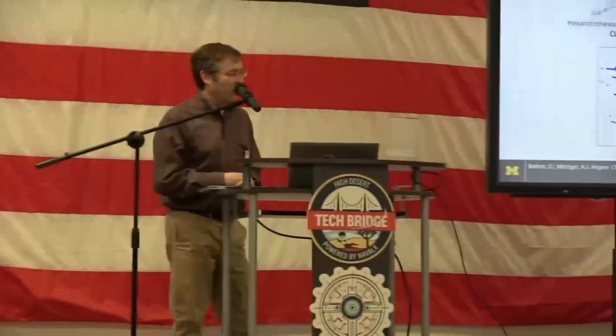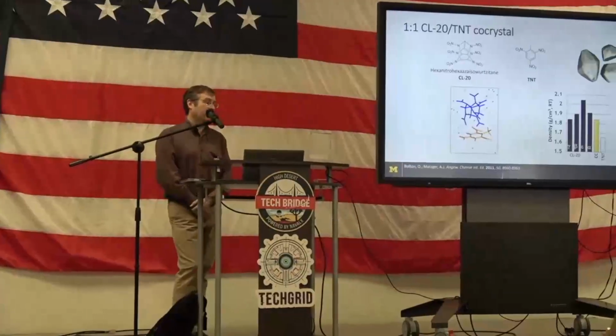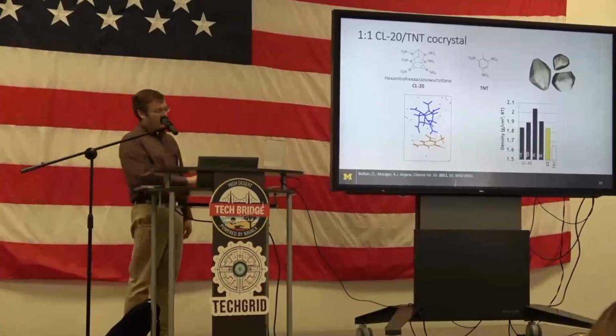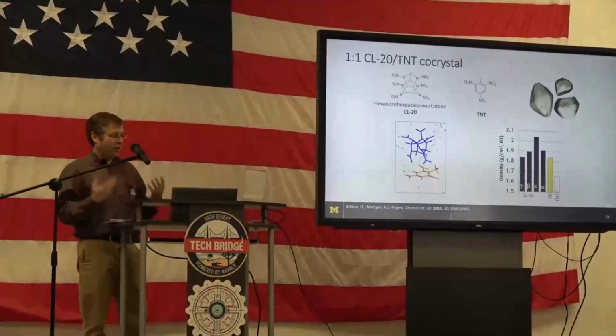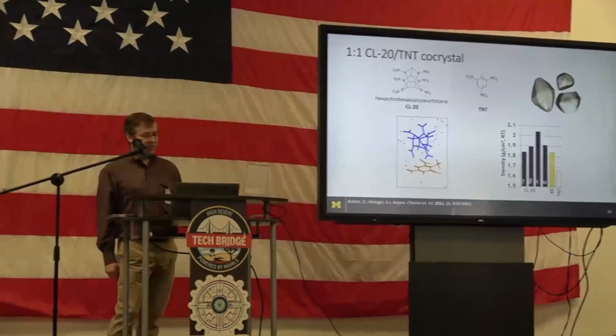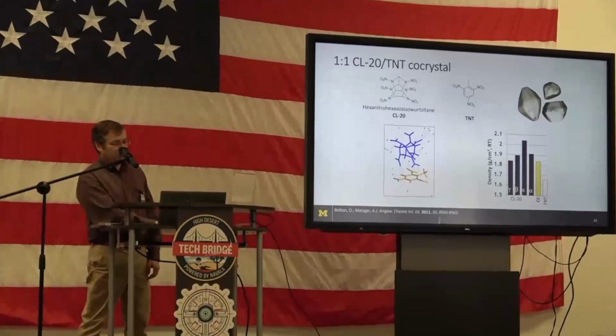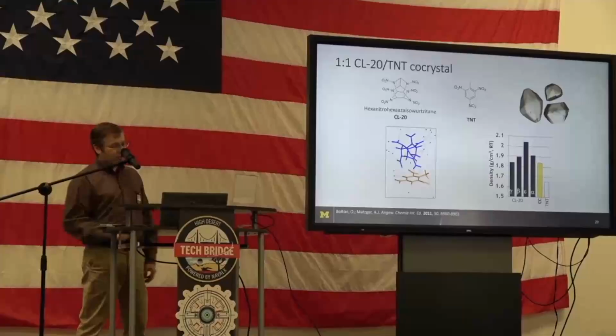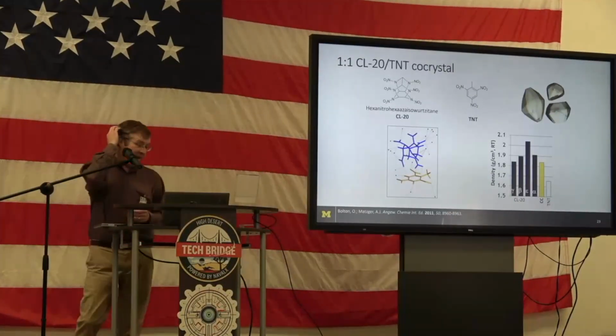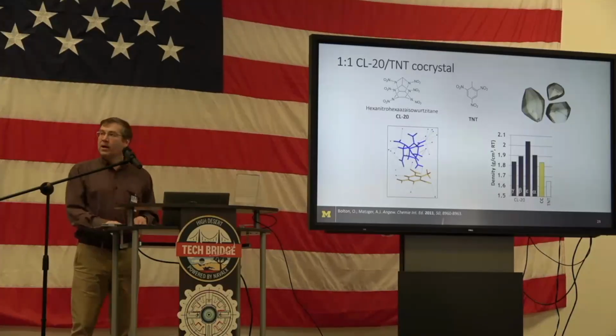Then we went on and started looking at energetic materials. We couldn't really apply this exact design principle to them because most of those do not have an electron-rich pi face to undergo this type of reaction. But it's okay, we can screen and hope. And that's what we did. This was our first hit, and really the first energetic co-crystal: a one-to-one co-crystal between CL-20 and TNT. There certainly are some interactions that look consistent with electrostatic interactions. The morphology is actually very nice. The density of the co-crystal was considerably better than TNT, better even than gamma CL-20, but not as good as the other forms of CL-20 in terms of total density.